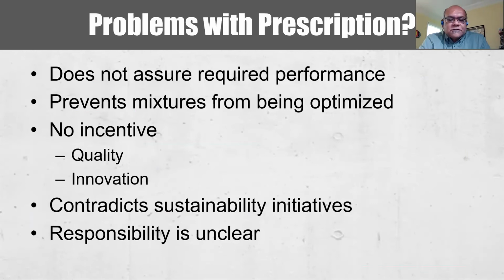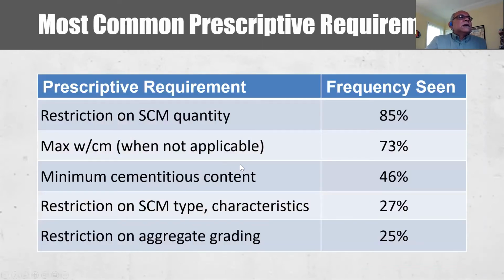It prevents the mixtures from being optimized, and it has no incentive for improved quality, because when you only have a strength requirement, let's say, you might get strengths that are significantly in excess of the strength requirement that is really unnecessary for that project. And very often prescriptive requirements will contradict with sustainability initiatives. We had an exercise where we reviewed about 120 specifications from various portions of the US, and we basically quantified the prescriptive requirements, and these are the ones that we think are most onerous to concrete producers in terms of optimizing concrete mixtures for performance.